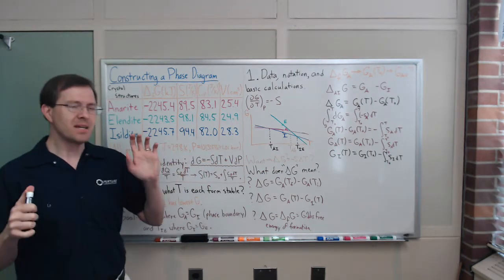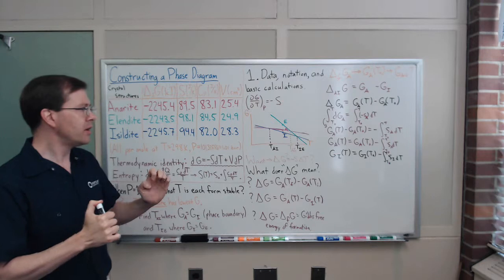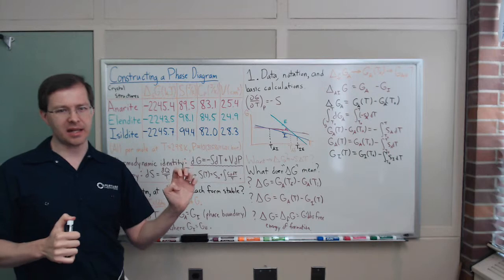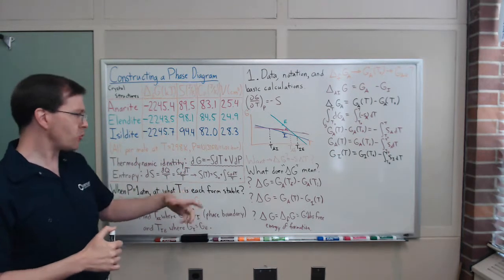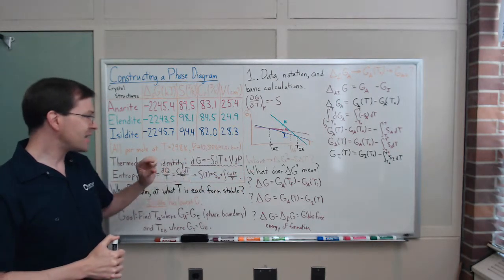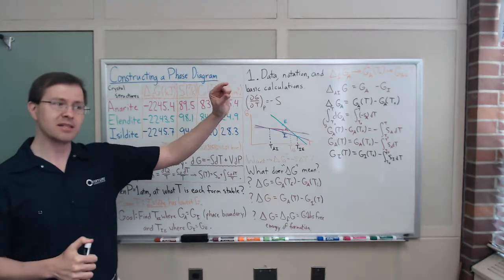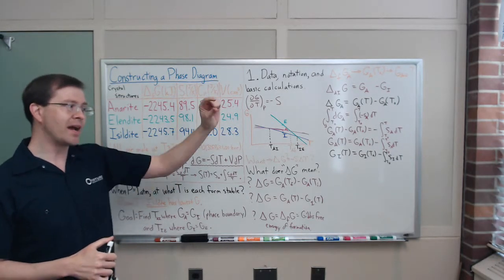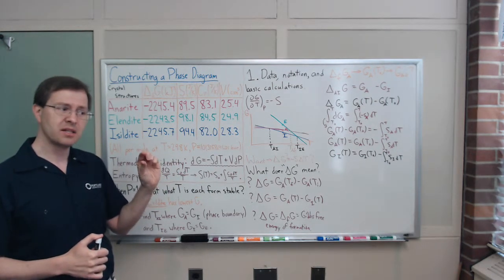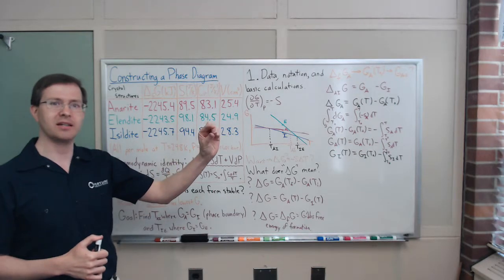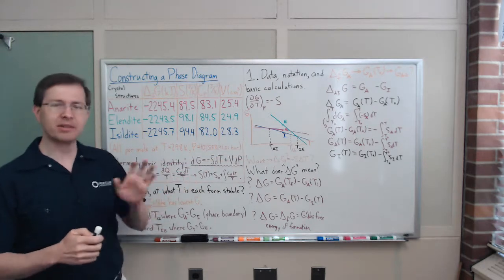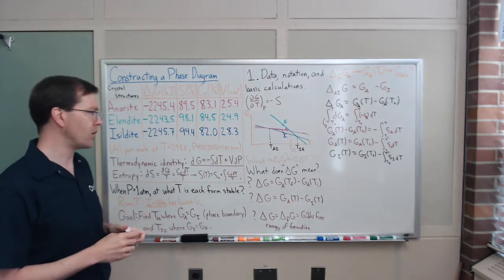And it turns out, here's the approximation we're going to make. I know that the entropies are changing a lot with temperature. But I'm optimistic that as temperature rises, both entropies will rise in similar ways. So even as they both rise, I'm crossing my fingers that the difference between those entropies is going to stay closer to constant as temperature goes up. It's a little ambiguous. We'll talk about it next time, but that's what I'm going to do to make this approximation a little better.